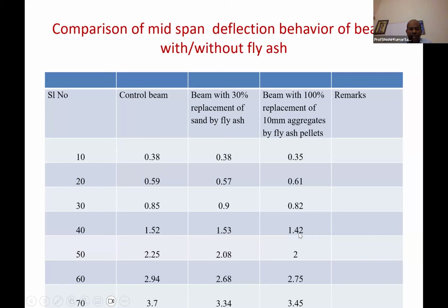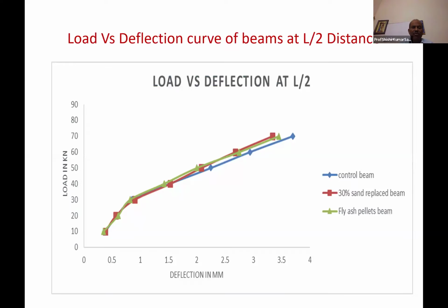You can see with fly ash pellets, the deflection is decreasing. Its deflection is decreasing, meaning it is showing its stiffness. Same thing with fly ash also. This is the low deflection curve. Whatever we have seen in the previous slides, the same thing is in graph form.